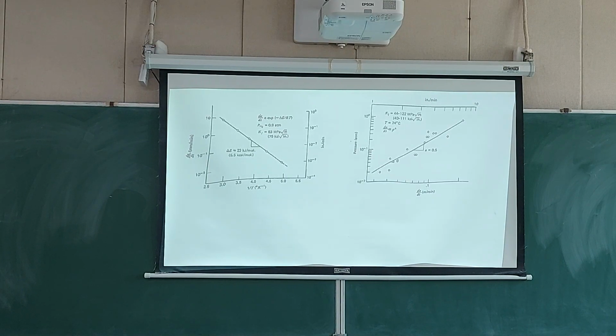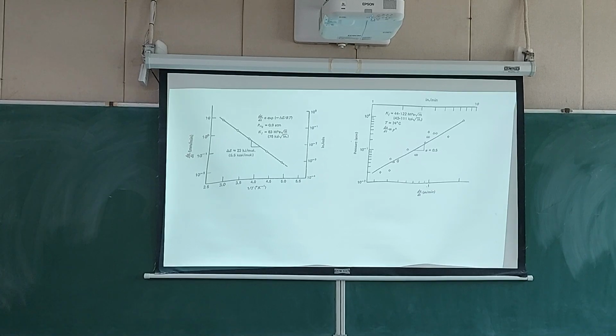On the right hand side, you have the plot of pressure versus dA by dt, and as the pressure increases, up to 1 atmospheric pressure as the maximum, dA by dt is increasing. This is the test at room temperature, and on the left hand side in this figure you have a dA by dt correlation in the form of the Arrhenius equation. dA by dt is directly related to the rate of reaction, and that has an activation energy dependent on temperature, so you have that Arrhenius type of equation. As long as the mechanism of reaction is not changing, your activation energy will also not change.